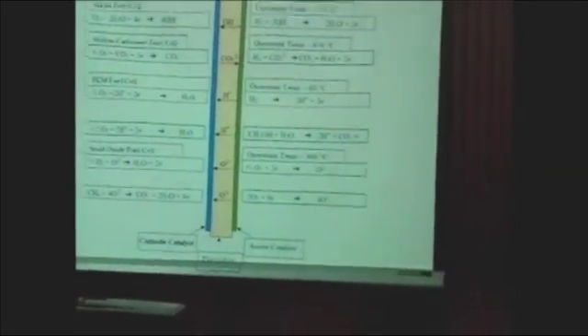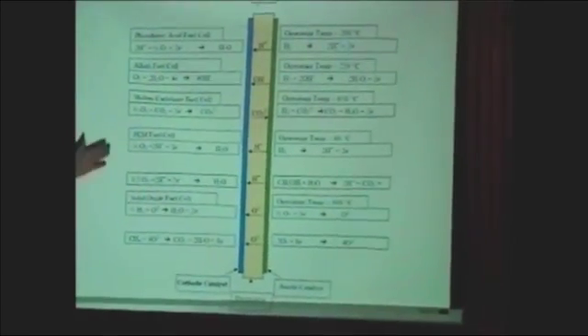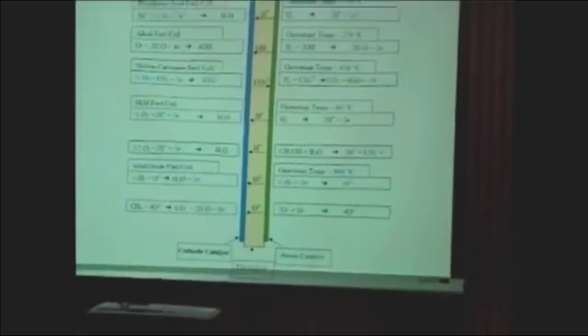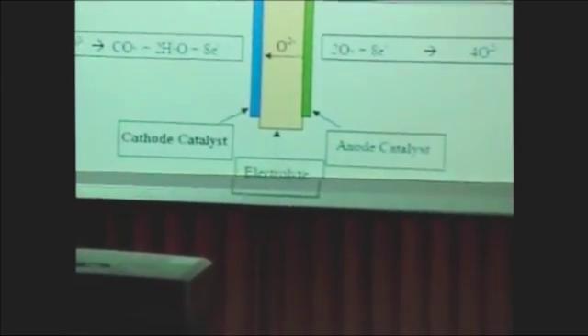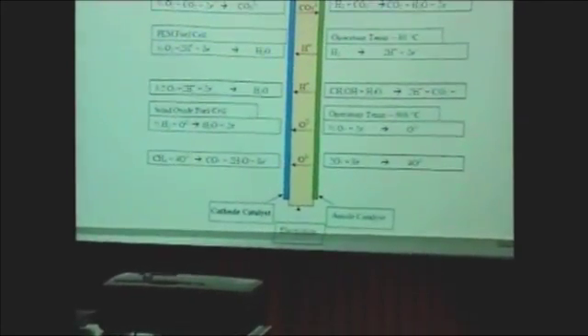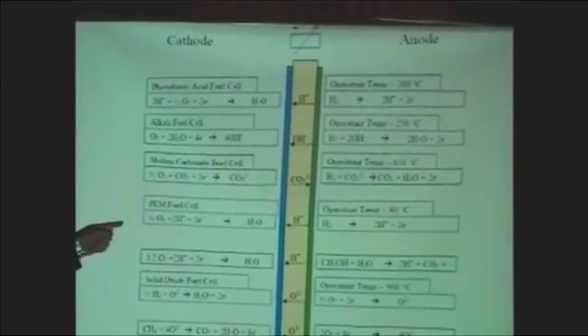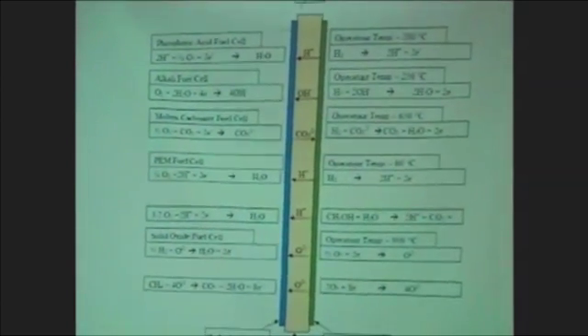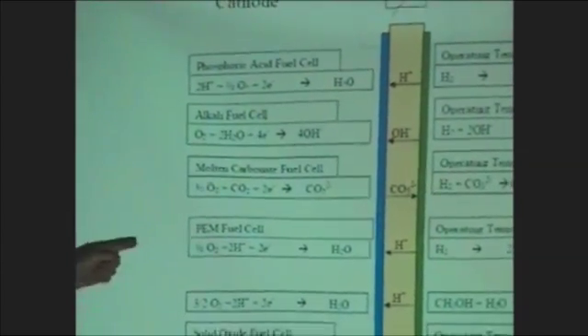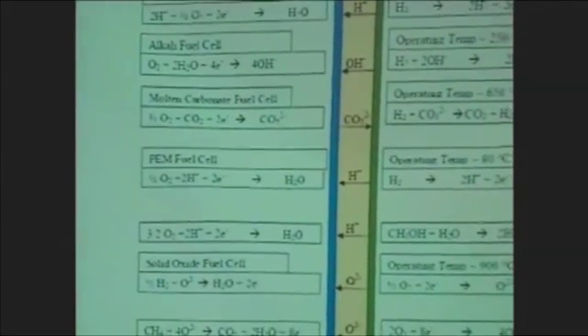The two most common types of fuel cell are the proton exchange membrane fuel cell and the solid oxide fuel cell. There has been a lot of research in this area, and hydrogen is considered an ideal fuel for these fuel cells, especially for proton exchange membrane, which only runs on pure hydrogen. As you know, if the carbon monoxide concentration is above 10 ppm, the carbon monoxide can poison the anode catalyst of the proton exchange membrane fuel cell. Proton exchange membrane fuel cells usually operate below 100 degrees C. It's considered a low temperature fuel cell, which gives a very high current density. The current density for the proton exchange membrane fuel cell is usually around 2 to 3 amps per square centimeter.